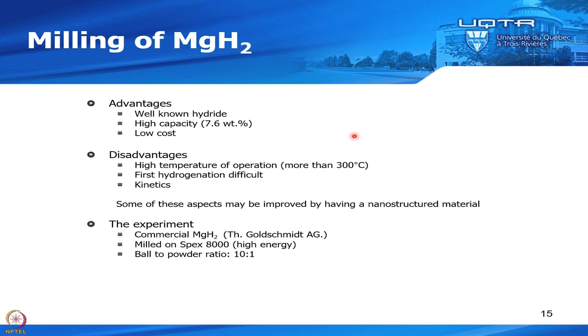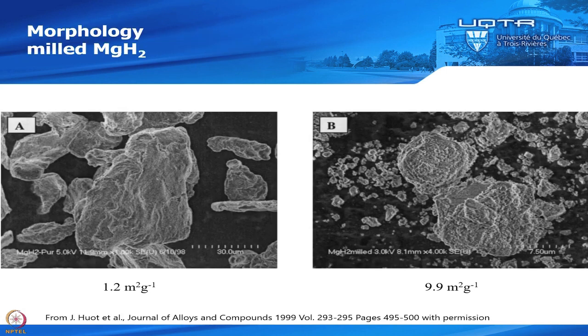So what I will show you today is the ball milling of commercial magnesium hydride in a high energy milling machine. This is the powder before milling and after milling for 20 hours. And the scale is not the same. Here this is 30 micron, here it's 7.5 micron.